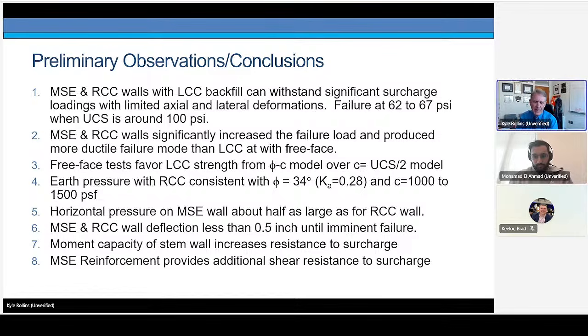The horizontal pressures on the MSE wall were about half as large as those for the RCC wall because the reinforcements are picking up load. Wall deflections for both the MSE and the RCC wall were less than about ½ an inch until we were getting very close to failure. The moment capacity of the stem wall is increasing the resistance to surcharge and can be accounted for by using the moment capacity of the stem. The MSE reinforcements themselves provide the additional shear resistance to surcharge, and you can account for their effect using slope stability techniques.